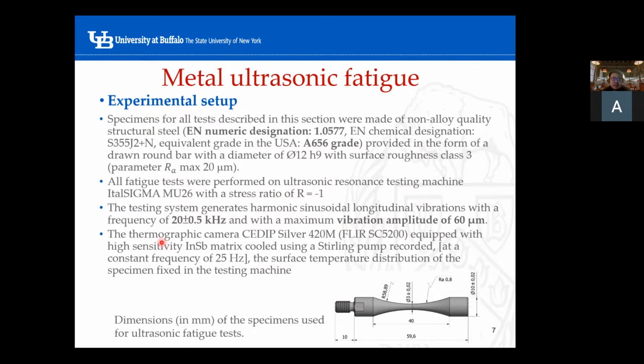During the test, we use a thermographic camera to capture the temperature variation, focusing on the gauge center, because we know the temperature increase in ultrasonic vibration fatigue will be very different than conventional high cycle fatigue. We monitor this temperature and derive a thermomechanical equation, trying to compare the simulation data with the actual monitored temperature. That's the reason we set up a thermographic camera here.